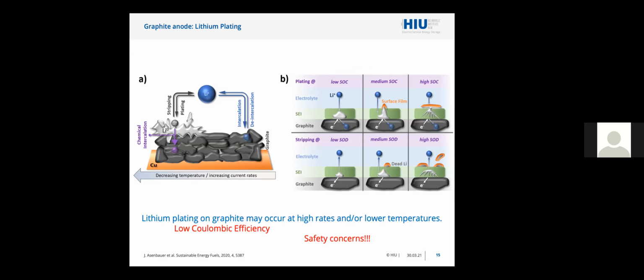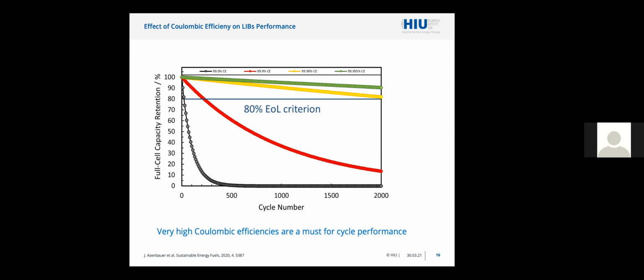Another problem of graphite electrodes, especially when the cell is charged at very high current or very low temperature, is lithium plating. I know that the group of the previous speaker, Margaret, demonstrated that lithium metal plating occurs almost always on lithium-ion cells. This is acceptable up to certain levels. Nonetheless, whenever lithium plating occurs, lithium metal can react directly with the electrolyte, and this leads to low Coulombic efficiency, but also to safety concerns, because some spontaneous reaction can start and develop heat, and this would then end up with some dangerous failure of the cell. So lithium plating is definitely a serious problem, but also Coulombic efficiency.